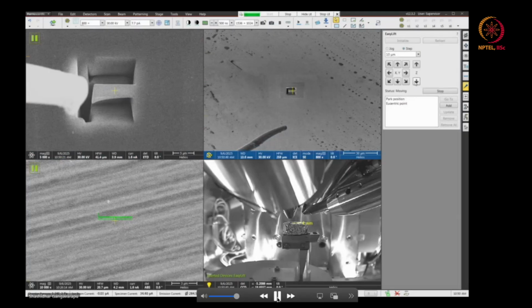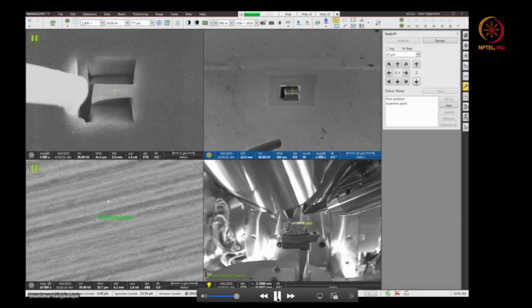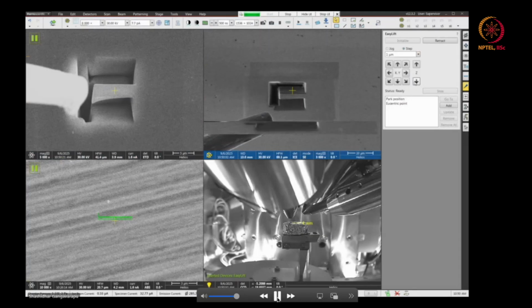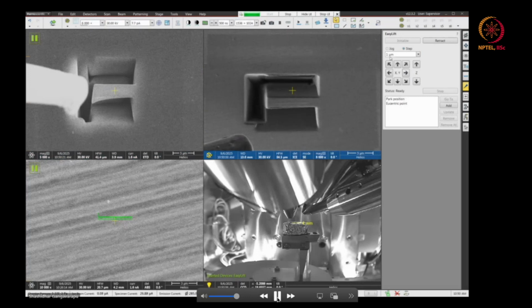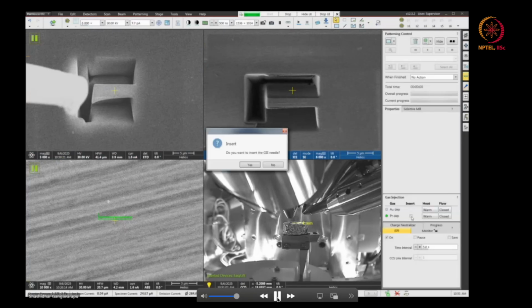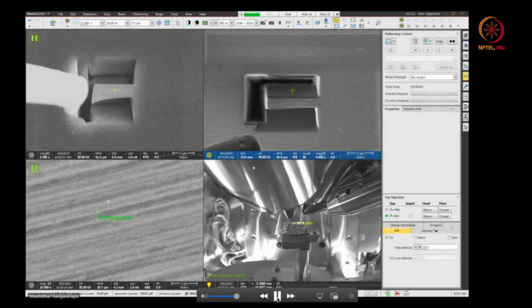Now I am going downwards, using this joystick. So basically I am going down, and once it has reached almost near the sample, it's best to insert the platinum needle. Now I am inserting the platinum needle to weld my sample with the manipulator.